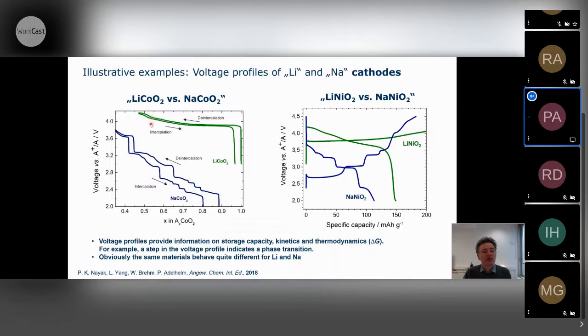And the reason for this is simply because you have a very nicely sloping voltage profile at high voltage, so around 4 volts, and in a very narrow voltage window. So most of the lithium ions are stored with the same amount of energy being released or being stored. And if you do the same thing for sodium, you can see the behavior is very different. So the capacity is comparable, but the voltage where the sodium storage occurs is a little bit lower compared to lithium, and also is distributed over a much wider voltage range.